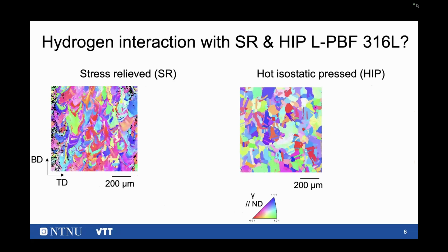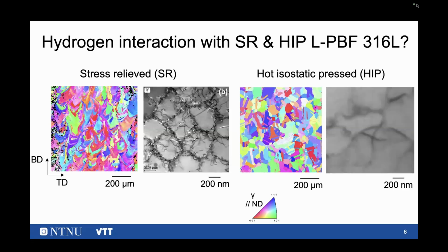So we decided to focus on those two post-treatments: on the one hand, the stress relieved condition, on the other hand, the hot isostatic pressed condition, because both on the micro level as well as on the nano level, they have a different microstructure. We see in the stress relieved condition that there are still a lot of dislocation cells present. They were not resolved after the stress relief heat treatment at medium temperature, whereas they are almost totally resolved after the hot isostatic pressing condition.